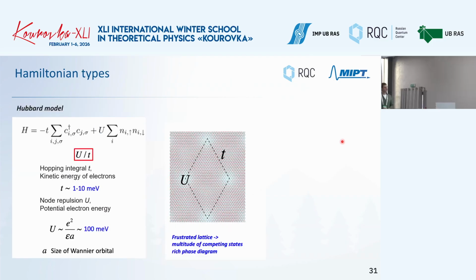Very important, these structures can be described by the Hubbard model. The Hubbard model basically has two terms: the kinetic energy of electrons, which is around 1 to 10 millielectron volts, and the potential electron energy, which in this case is around 100 millielectron volts. By rotating the angles, you can modify the kinetic energy, and by changing the gating, you can modify the potential electron energy. So in your material, when you have your stacked layers, you can obtain different Hamiltonians,